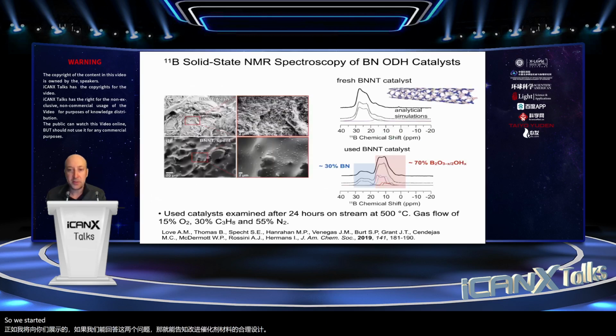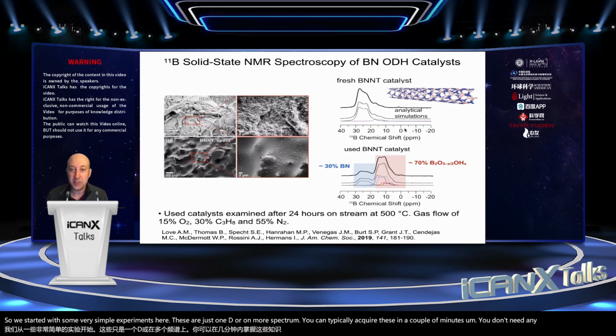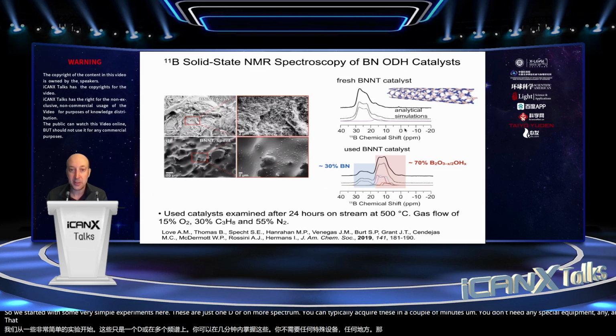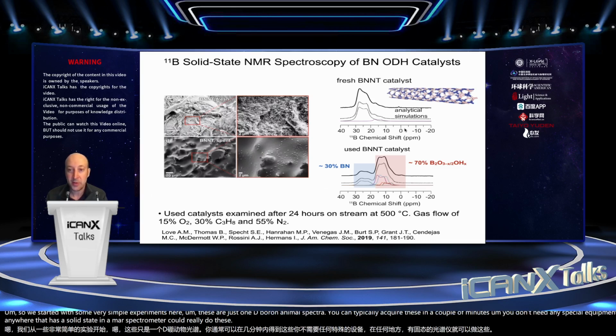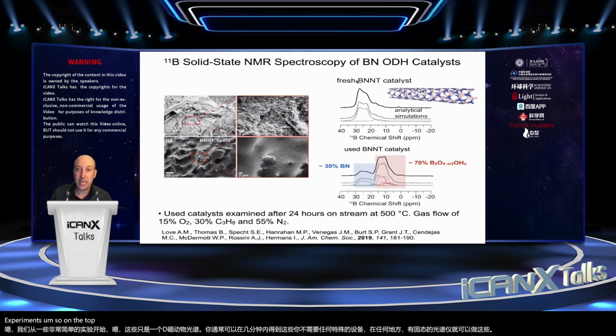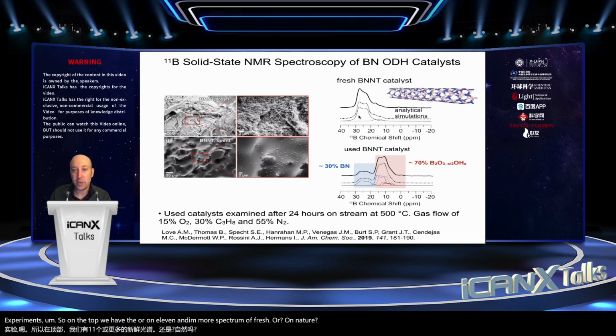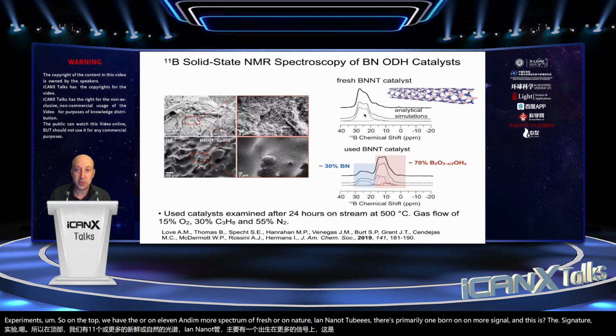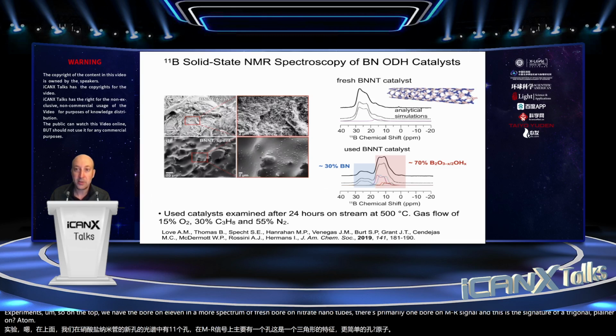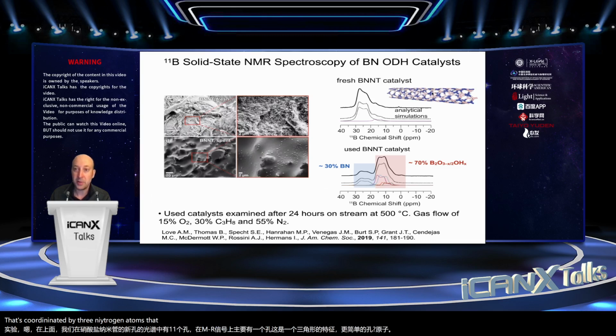So we started with some very simple experiments here. These are just 1D boron NMR spectra. You can typically acquire these in a couple minutes. You don't need any special equipment. Anywhere that has a solid state NMR spectrometer could really do these experiments. So on the top, we have the boron-11 NMR spectrum of fresh boron nitride nanotubes. There's primarily one boron NMR signal, and this is the signature of a trigonal planar boron atom that's coordinated by 3 nitrogen atoms. So those would be the boron atoms that make up the bulk structure of boron nitride nanotubes.